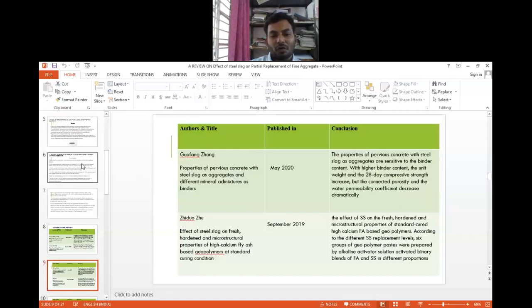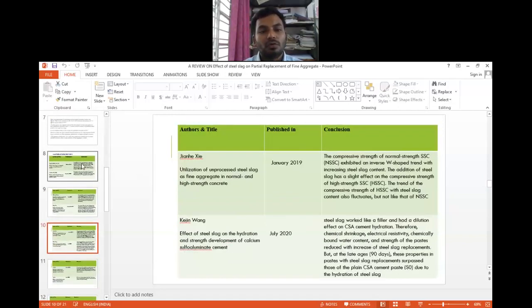Next, Zhidao Zhu. The effect of steel slag on the fresh, hardened concrete and microstructural properties of high calcium fly ash based geopolymers under standard curing conditions, published in 2019. He concluded on steel slag in the fresh, hardened concrete and microstructural properties of the standard curing of high calcium fly ash based geopolymers with steel slag fine aggregate. He used the admixture as a geopolymer. He got the optimum strength, and his results give the maximum strength compared to the normal strength.